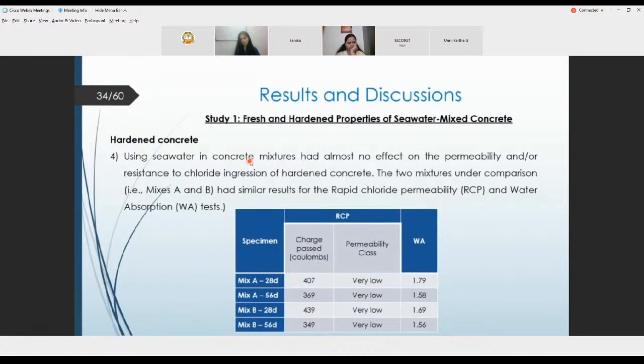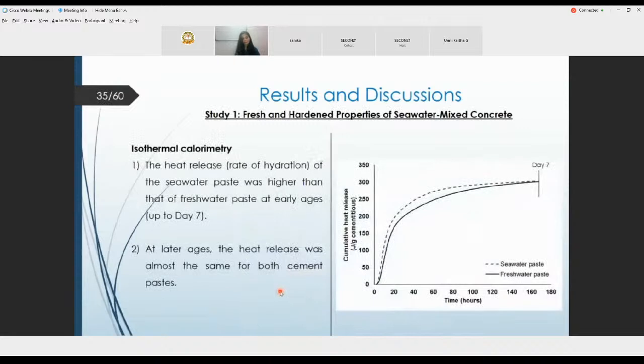Also, using seawater in concrete mixes has almost no effect on the permeability and resistance to chloride ingression of hardening concrete. The two mixtures under comparison, mixes A and B, had similar results in terms of rapid chloride permeability and water absorption, as per the results here.